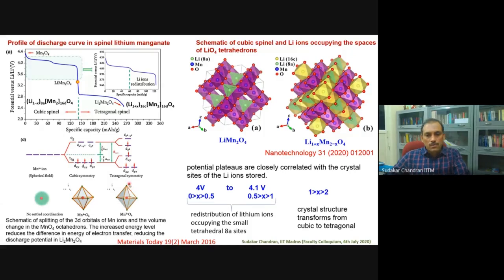The distortion comes because of the Jahn-Teller effect. The manganese in 4 plus, when it becomes manganese 3 plus, there's the electrostatic repulsion between the oxygen 2p non-bonding orbitals and the d orbitals, which leads to the distortion of the octahedra, and that makes the cubic spinel structure undergo a transition to the tetragonal spinel structure. In fact, in the very first charging discharging cycle also, you can see 2 steps, and that is associated with the redistribution of lithium ions. So this particular structure told many things.